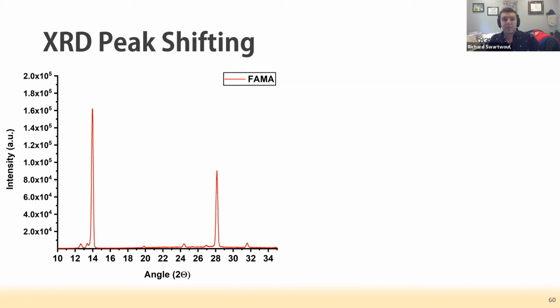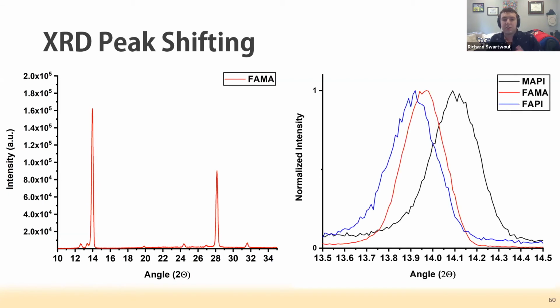If we look at the characteristic peak around 14 degrees, we can again show a shifting toward lower angles between the methylammonium lead iodide and the formamidinium FA-MA film. Plotted here also is a pure formamidinium lead iodide film deposited from a DMF-based precursor.